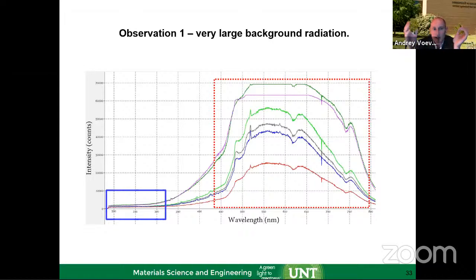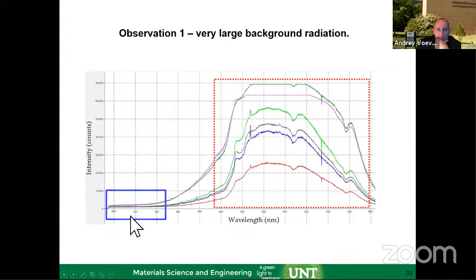Once we start looking at it, here is the full spectrum from UV all the way to near IR, a region here to 800, so through the visible range in here. You can see that, first of all, yes, we can start seeing some peaks appearing, but we also notice right away that we have a lot of background radiation, because we're also heating the melt pool and emitting white light in the continuous spectrum. We also have bremsstrahlung radiation, which is recombinations of electrons with the gas ions in here.